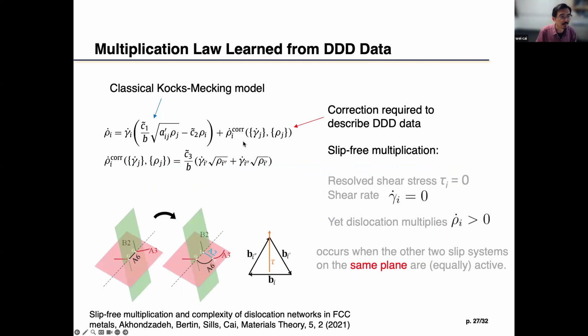The other thing is the multiplication rate, right? Because in order for this ODE to run, you need to know how the rho evolves. And this is where we try to compare with the DD data, which suggests that in addition to the classical Kocks-Mecking model, you have to add a correction term to it. Because the Kocks-Mecking model says that the dislocation multiplication rate is proportional to the shear rate. That means if there's no slip activity on a certain plane, there should not be any multiplication, which is quite a reasonable thing to assume. But the DD data suggests that actually there are cases in which a slip system has no activity because there's no resolved shear stress on it, but it still multiplies, okay?